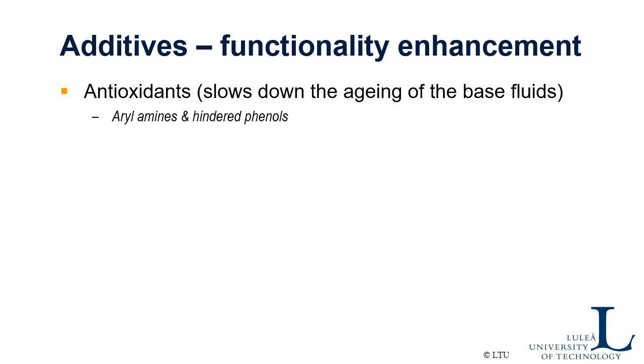And one category is the antioxidants. The base oil itself will oxidate from water and oxygen coming into the lubricant, and then acids are formed, and those acids may corrode the surfaces and destroy the surfaces. So you really need to control the oxidation of the base oil.